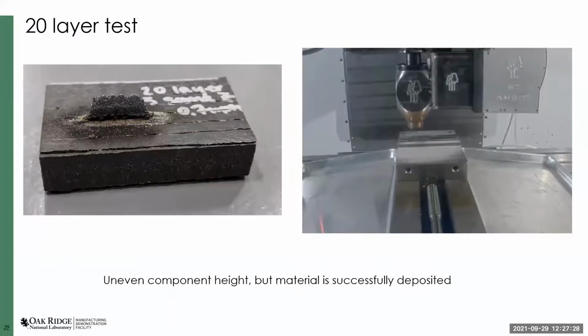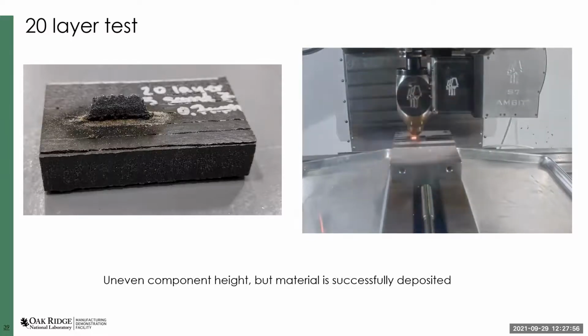But I also wanted to see what happens to the polymer longer term, because if you're building up layers, the polymer is no longer being exposed to the laser directly, because the laser is now on top of this deposited metal. But you do have a component that's a couple hundred degrees Celsius that's resting on top of your polymer, which has a melting point of a couple of hundred degrees Celsius. So here I have a video of the process.